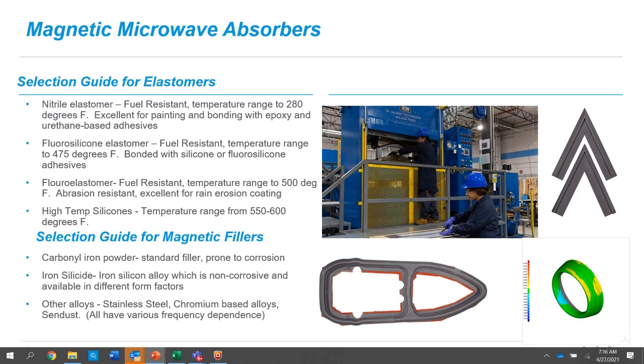So the ones that we recommend, our standard commercial product line, is silicone, just standard silicone, which is a great material to use, but it does not withstand things like solvents. It's poor in fluid resistance. So we've qualified nitrile rubber as a very fuel resistant material. It's got a good temperature range to 280F. Easy to bond and paint, so it can be bonded with standard epoxies or urethane adhesives. Standard paints adhere well to it, which are also issues for silicone-based ones. So that's a good standard general material that meets all the fuel resistant requirements that you'll have.